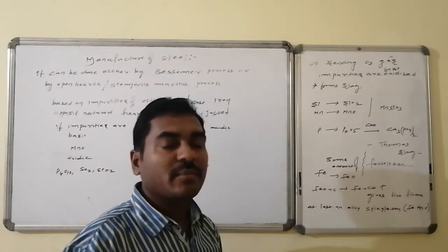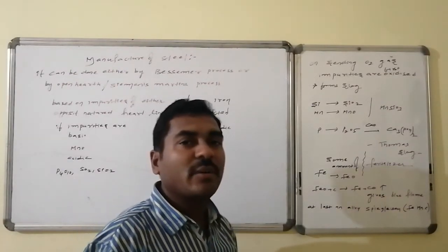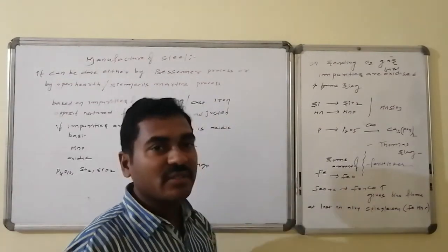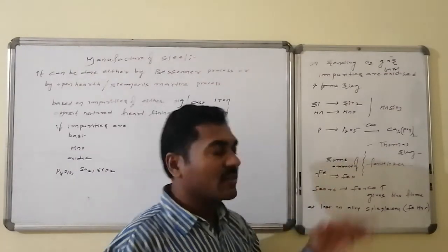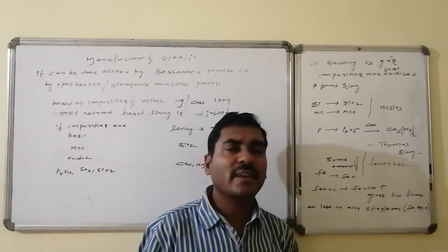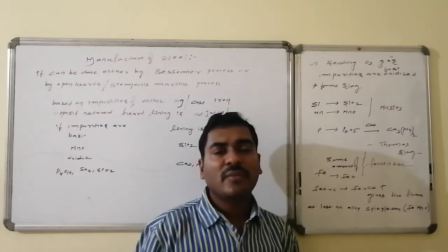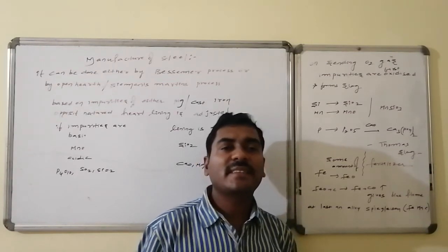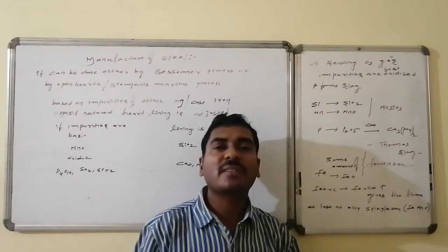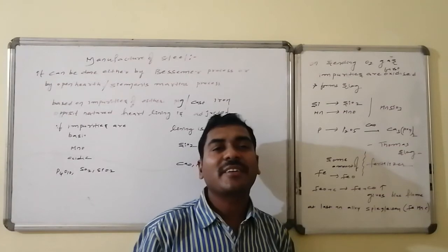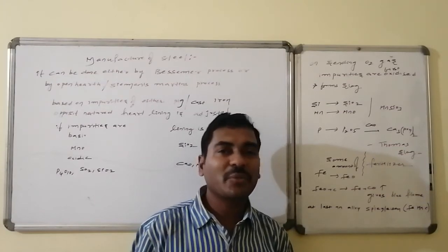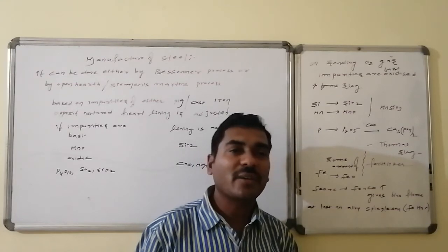The carbon present as impurity in this cast iron, otherwise the pig iron, undergoes oxidation by reducing the ferrous oxide, hence it is converted to carbon monoxide. Carbon monoxide is a volatile gas, so it is removed apart from the slag. It burns with a blue flame because of the high temperature. Once the blue flame is off, it means the carbon content is completely removed. Now after removal of carbon content, we want to prepare steel. Steel has some amount of carbon content.